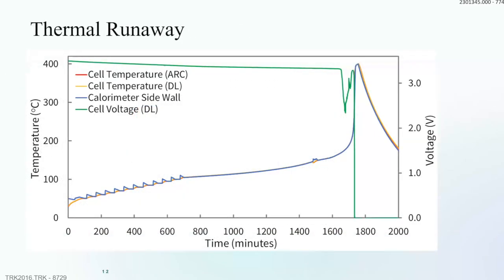One way to characterize thermal runaway is using an accelerated rate calorimeter — a large adiabatic chamber where you slowly heat the cell in five-degree increments and wait to see if exothermic reactions occur. The sawtooth line represents the chamber wall temperature. Around 160–180 degrees, you see a first exotherm associated with the anode. Once the cathode begins reacting, you get a rapid vertical temperature increase. Voltage drops as internal shorts develop within the cell, and the external cell temperature can exceed 400 degrees C.